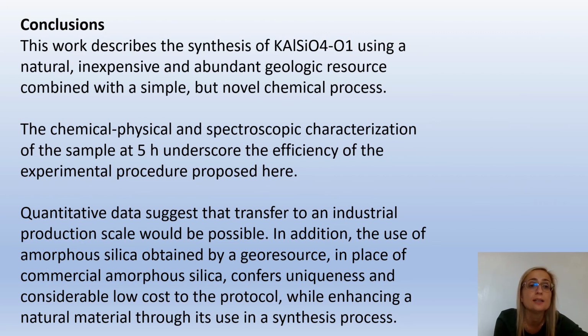In conclusion, we can say that this work described the synthesis of KAlSiO4-O1 using a natural, inexpensive and abundant geologic resource, combined with a simple but novel chemical process. A precursor prepared through a series of chemical treatments performed on a sample of diatomitic rock was hydrothermally treated at a temperature of 150 degrees Celsius and successively calcined at 1000 degrees Celsius. The presence of KAlSiO4-O1 as an isolated phase is attested in the time interval 2–5 hours.